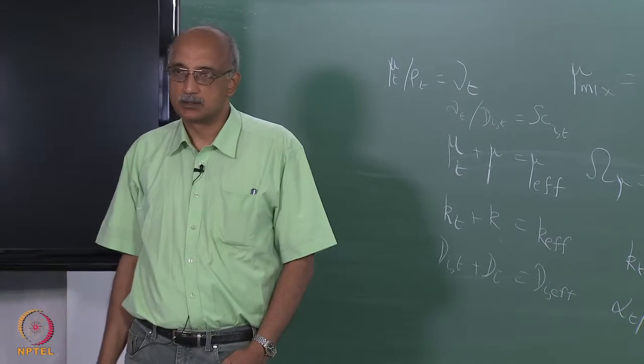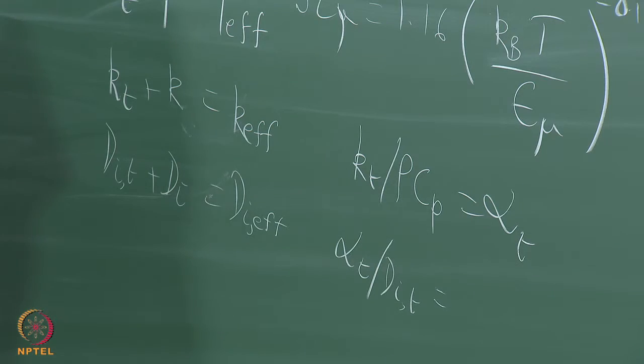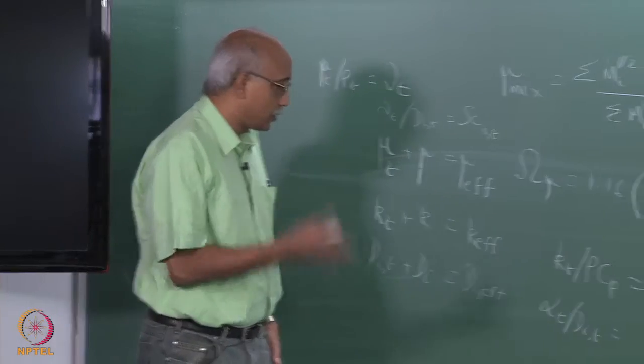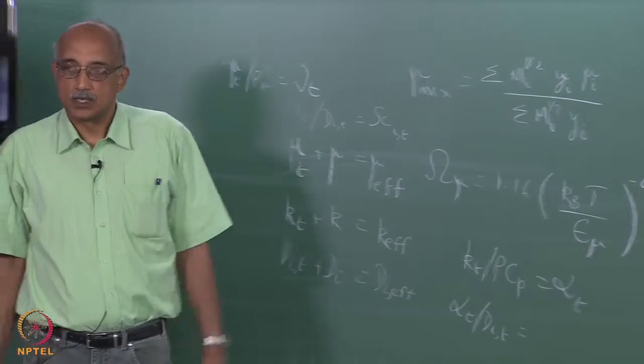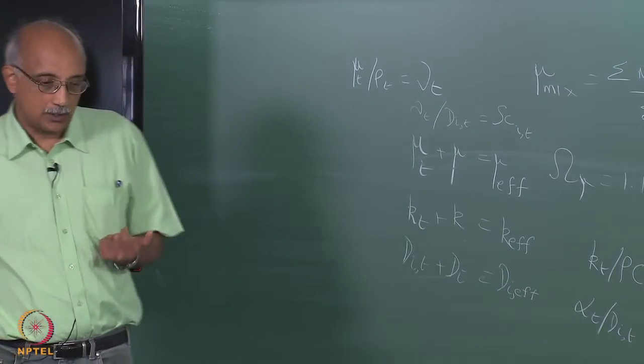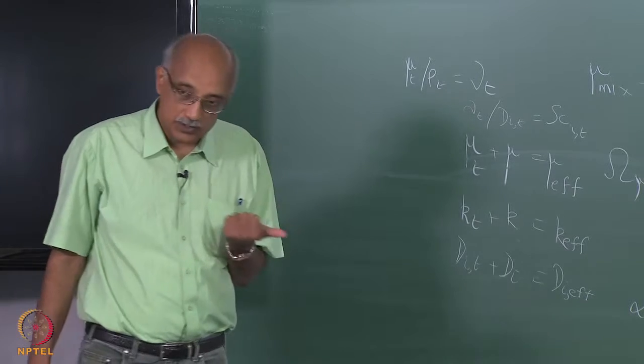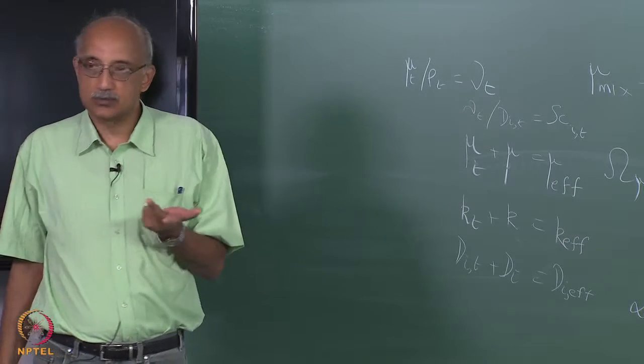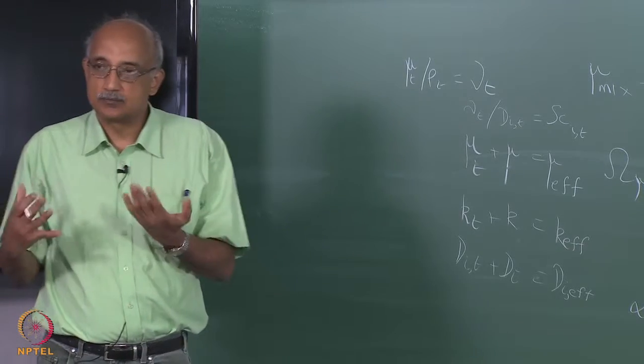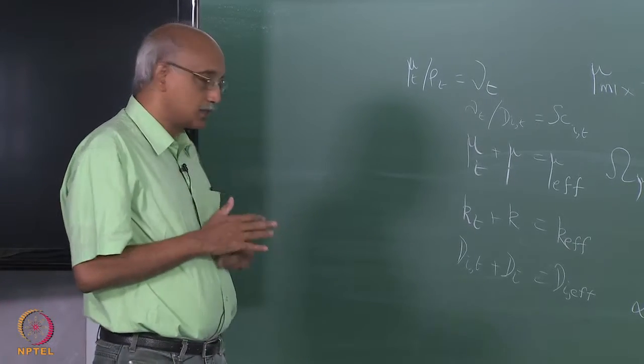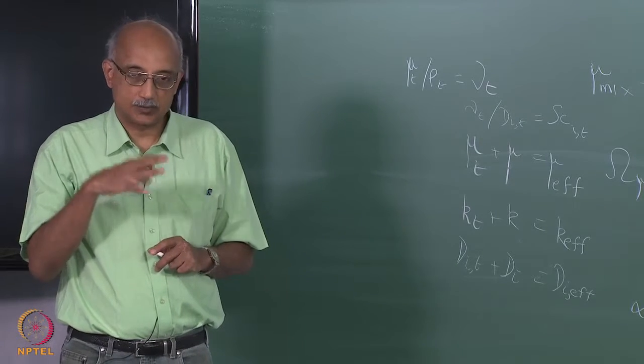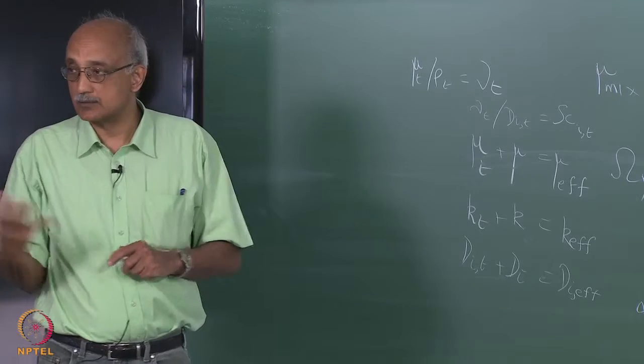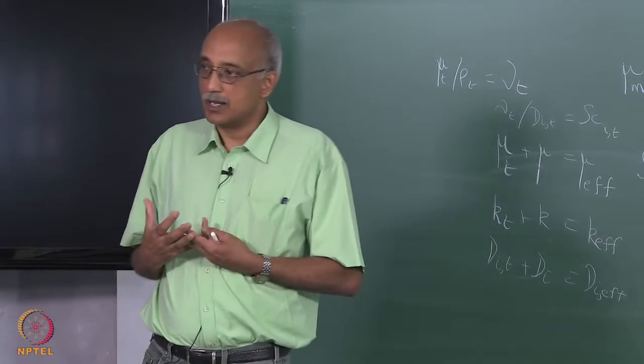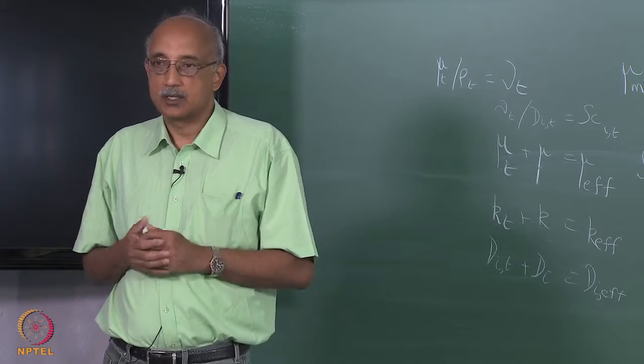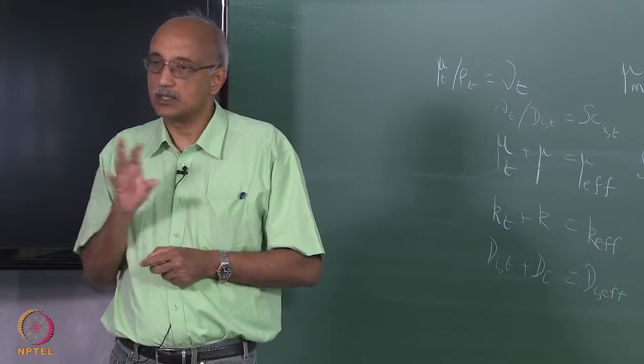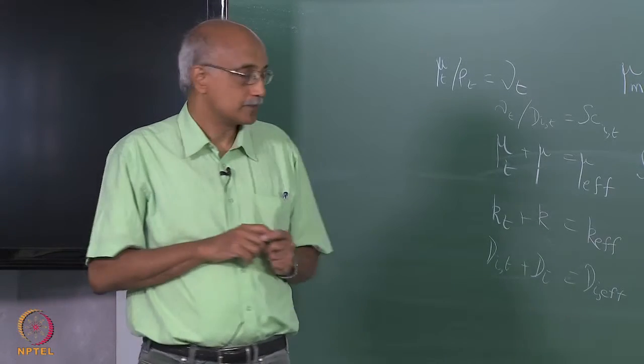Any idea what that is? Lewis number. So, the point is all these are actually close to unity. In other words, once turbulence sets in, the associated kinematic viscosity, thermal diffusivity and Fick diffusivity are all almost equal. In other words, once turbulence sets in, the effect of turbulence is much more predominant compared to the effect of the fluid itself. So, the nature of the fluid does not matter as much as the nature of the turbulence. However, under laminar conditions, it is the nature of the fluid that really determines these transport coefficients.